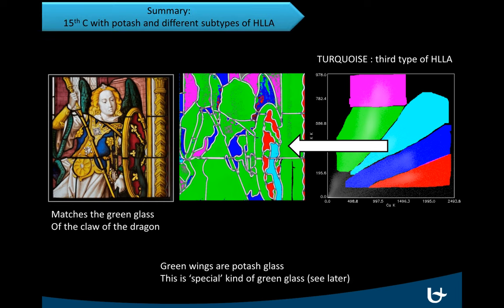In summary, we have a late 15th century window consisting mainly of potash glass and some high-lime, low-alkali glass — an outcome reported in literature before. In particular, the colorless and pot metal glass appears to be of the potash type, while the most expensive and sophisticated glass — the red, the blue, and the special green — is of the high-lime, low-alkali type. The potassium-calcium ratio seems to vary with the color of the glass.